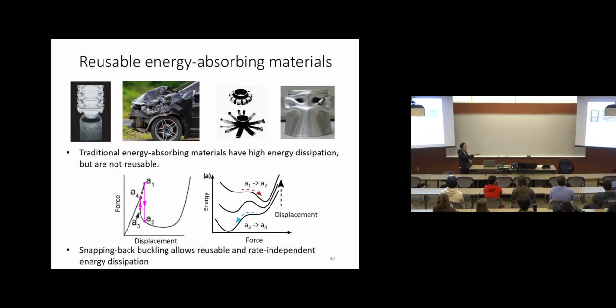So how is energy dissipated here? If you follow this force displacement curve, load the material up to this A1 point, and it will snap to this A2 point. Correspondingly, there's also a snap in the energy landscape. When you unload the material, it will first go back to the A3 point, then snap back to the A4 point, also corresponding to a snap on the energy landscape. The loading and the unloading do not overlap, but form a hysteresis between them, which indicates energy can be dissipated through this loading and unloading process. Moreover, once you unload, the material can completely recover and the deformation is completely elastic. Therefore, we would further expect rate-independent behavior.